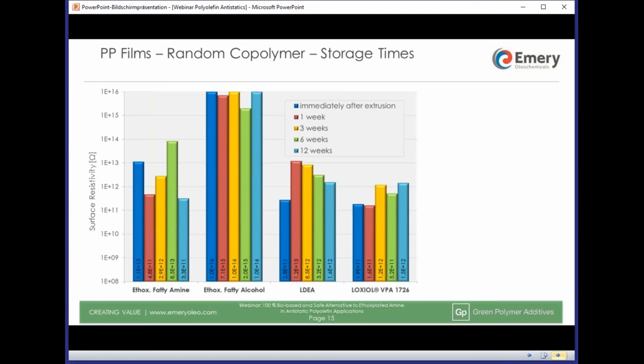Okay, first chart, PP random copolymer films, influence of storage time. What do we see? We see a bundle of columns for each of the 4 antistatic agents. On the left, we see the surface resistivity indicating the antistatic performance. So the lower the columns, the better the antistatic performance. And this antistatic performance was measured after certain storage times.